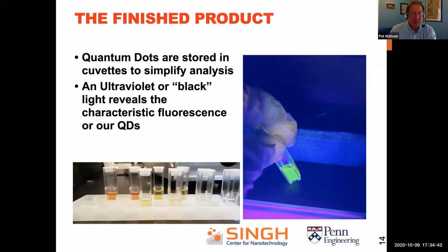We put these in these little cuvettes to make it easy to do characterization. And you can see on the right, we're using a black light, or ultraviolet light, and you can see this beautiful green color coming out of the quantum dots here. They're taking the ultraviolet light, creating electron-hole pairs, and then the electrons drop back down again at a very specific energy determined by the confinement effect. And we get this beautiful green. Other samples from this batch could be red or blue.